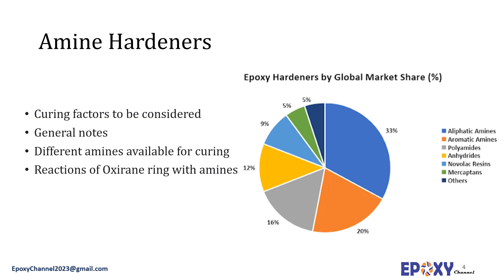The viscosity of the epoxy resin is another important factor to consider. The amount of required hardener is calculated based on the EEW (epoxy equivalent weight) of the epoxy resin and the amine value of the hardener, which has been covered in other videos. It is worth mentioning that the amount of hardener should be calculated and used properly — too much hardener decelerates the curing process leading to an improperly hardened product, while too little results in a partially cured system. Both are detrimental to the final properties.